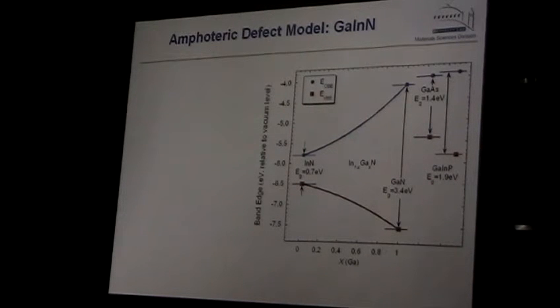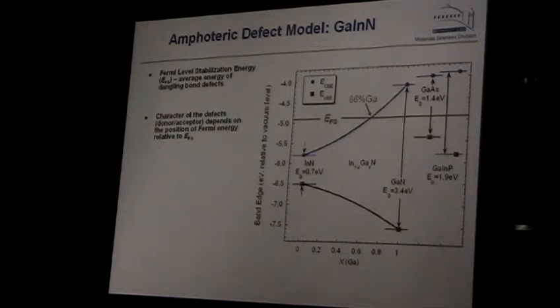So let's look now at the Fermi level stabilization energy, which is the energy of these native defects that we are introducing. You see that this level is in the band gap in gallium nitride, but it is well above the conduction band in indium nitride. And it makes a big difference, because defects in gallium nitride make gallium nitride insulating, since they move the Fermi energy into the band gap. Defects in indium nitride make indium nitride conducting. That's what we expected, so we thought we would check it with our radiation study.